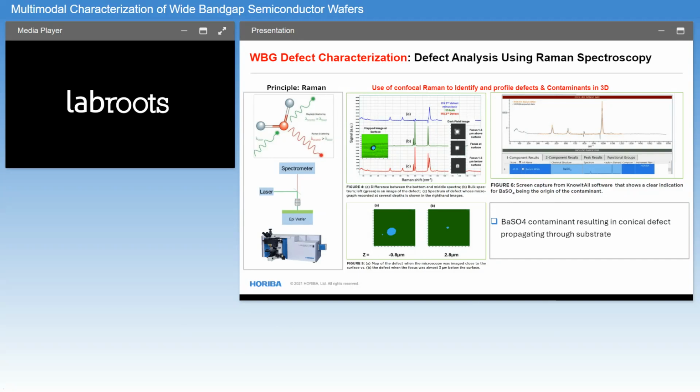And first we can see the geometry around the defect. It's basically bulk material. She has a Raman signature from that. And then, probing at the defect, she has both the signature from the surrounding bulk material as well as the peculiar signatures of the Raman of the defect itself. And with our software, you can take the difference of the two, which is the blue spectrum that you see at the top there, and that's really, in a sense, the identity of the defect.